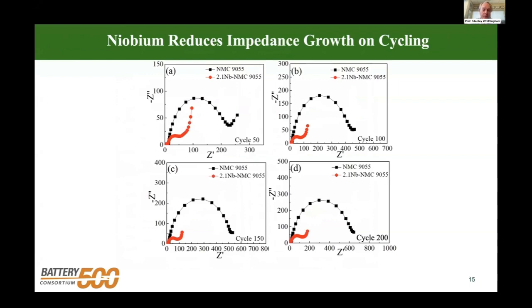Similarly, if we look at the impedance of these cells, this is after 50 cycles, no niobium, a little bit of niobium. You can see a difference here. After 100 cycles, 150, 200 cycles, again, niobium is preventing the formation of these resistive materials on the surface of this high nickel material. So this is, again, an indication we can use high nickel materials.